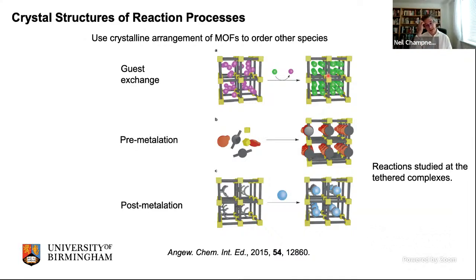So there are two different strategies to making such systems. One is that you have a metal complex which can also act as a ligand, and you use it as a ligand to make a framework. I'll give you an example of that in a moment. This then orders the metal complex in 3 dimensions in your crystal, and you can look at different processes at that metal complex. The other strategy is what's called post-metallation, and here you make a framework structure which has vacant binding sites on the framework. And then you can introduce a metal complex after you form the framework, and the metal complex becomes bound to the vacant binding sites, becomes ordered, and then you can study the reaction processes by crystallography.